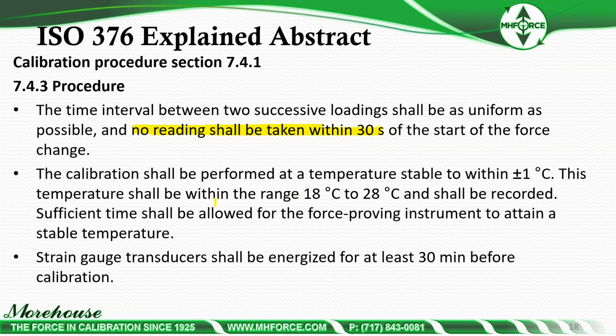This temperature shall be within the range of 18 degrees C to 28 degrees C and shall be recorded. Sufficient time shall be allowed for the force proving instrument to attain stable temperature. That's typically on the end user, the mass of the material, everything else that will determine how long an instrument needs to acclimate to room temperature.